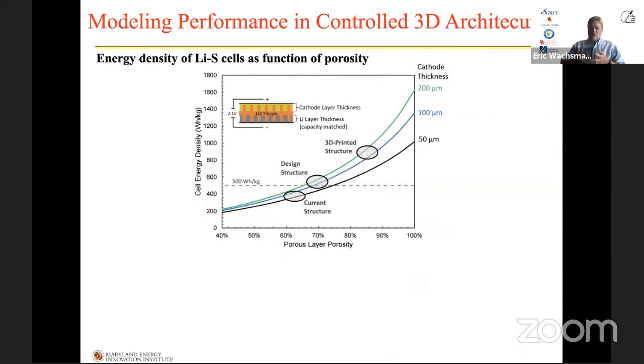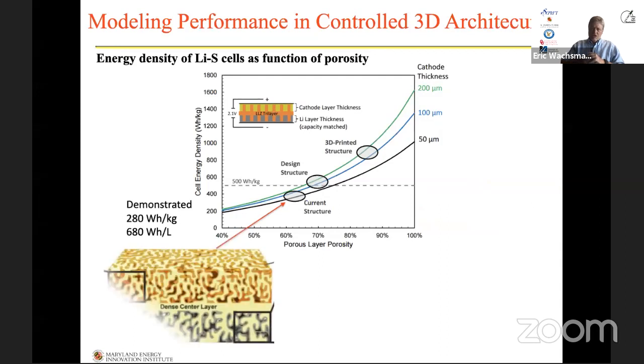And then ultimately, we want to be able to calculate what type of energy density we would get. And so this is for lithium sulfur cells that we've been making, not 3D printed, but actually made using conventional tape casting and laminating and firing. We're making these types of lithium sulfur cells and getting on the order of about 280 watt hours per kilogram. If you're familiar with batteries, your best Panasonic is somewhere around 240 or something like that. So it's actually a higher energy density than conventional batteries today.